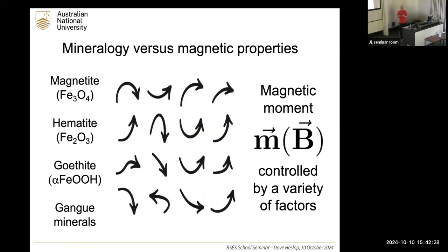And this is where often there's a disconnect between mineralogy and magnetic properties. So we've got iron oxides like magnetite and hematite, we've got goethite, which is an iron oxyhydroxide, and then we've got various gangue minerals. Now, even if somebody was able to tell you, oh, this bit of ore is made up of this percentage of magnetite, this percentage of hematite, and so on, you would struggle to actually work out what the magnetic moment is as a function of the field, because this is controlled by a variety of factors beyond simply the mineral composition.